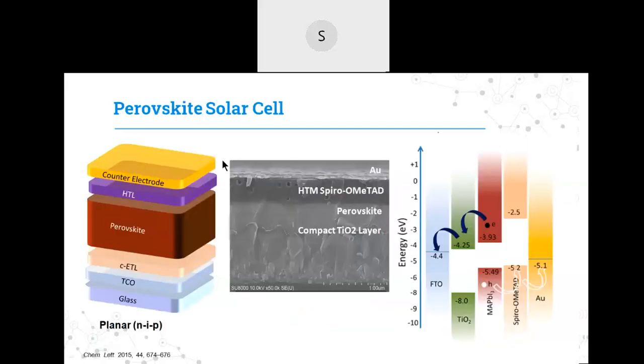Let's understand the perovskite solar cells. We need a few layers to be deposited along with the perovskite absorber to make it a solar cell. Considering a planar NIP structure, we have a conducting glass. Over that, we deposit a compact electron transport layer, which is used for the collection of electrons. Possible examples for these electron transport materials are titanium dioxide and tin oxide.